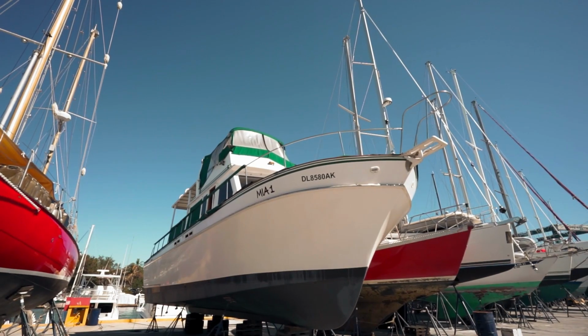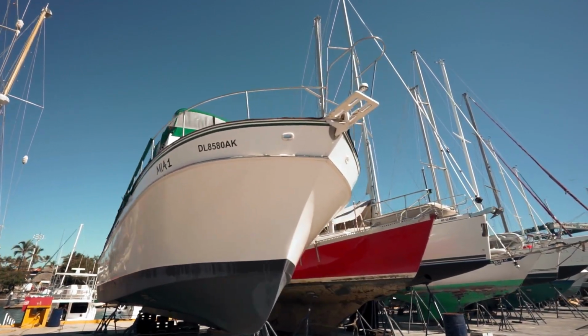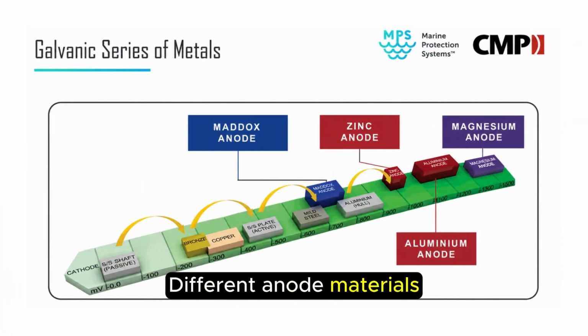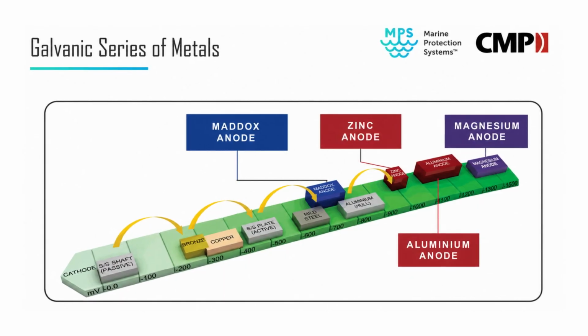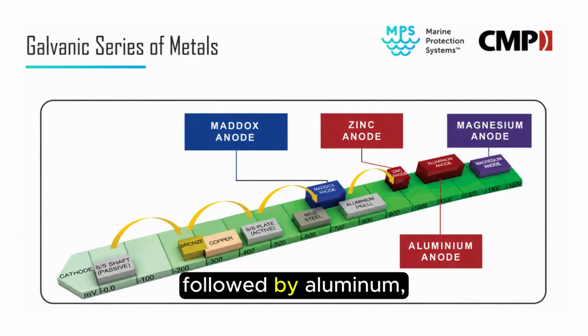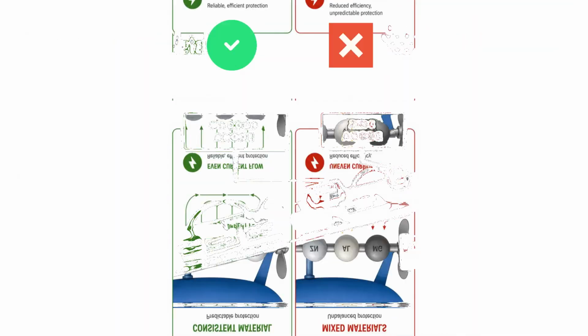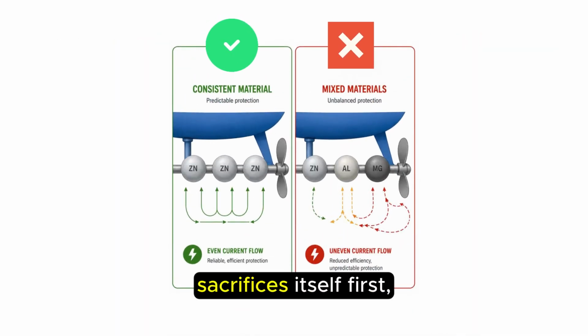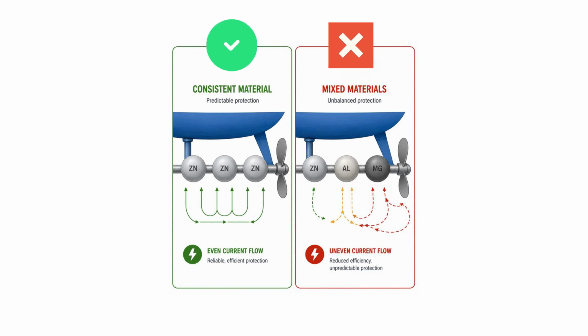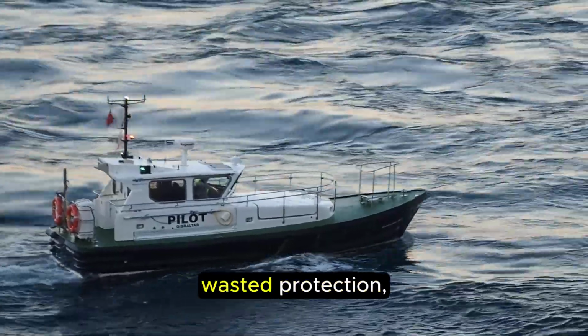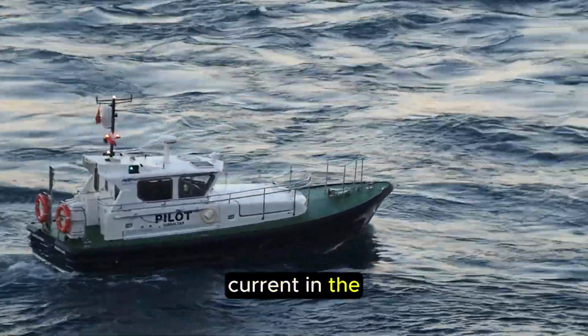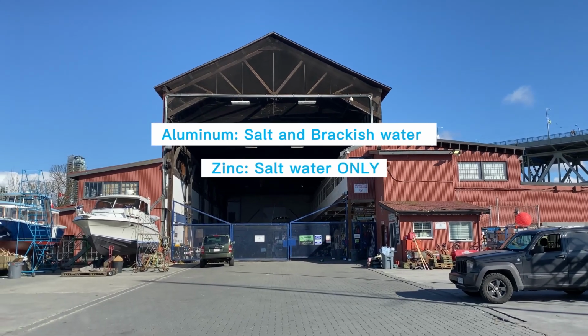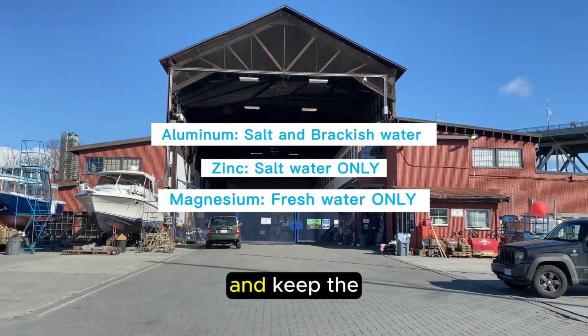Can you mix zinc, aluminum, and magnesium? You shouldn't. Different anode materials have different activity levels. Magnesium is the most active, followed by aluminum, then zinc. When mixed together, the most active metal sacrifices itself first, often protecting the other anodes instead of protecting your boat. The result is uneven wear, wasted protection, and sometimes excessive current in the system. The best approach is consistency. Match the anode material to the water type and keep the system uniform.